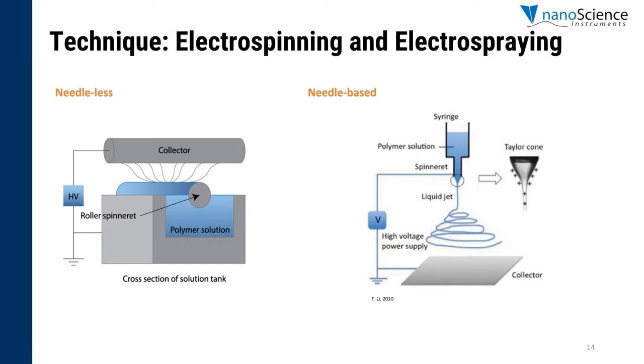In both cases, the polymer solution is exposed to a specific voltage to create an electric field between the solution and the collector. Once the surface tension is overcome by charge accumulation, a solution jet is ejected, and due to bending instabilities and whipping motion, the solvent evaporates and a solid fiber is formed.